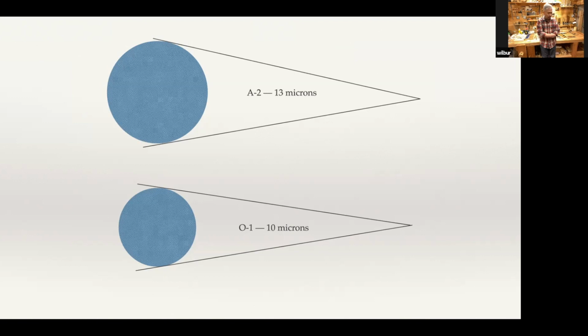And if you talk to people who've tried out both A2 and O1 steels, they may not know about the carbide size or any of the metallurgy stuff that we've been going through, but they will tell you things like this. Oh, I like my paring chisels to be made out of O1 because I can get a finer edge out of them. Or I like using A2, but I find that I have to sharpen it with a higher bevel angle, maybe going to like 32 or 33 instead of 30, because if I sharpen it to 30, then the edge crumbles too quickly. And that may be because with such a shallow angle, those carbides are just popping out at the edge of the chisel.